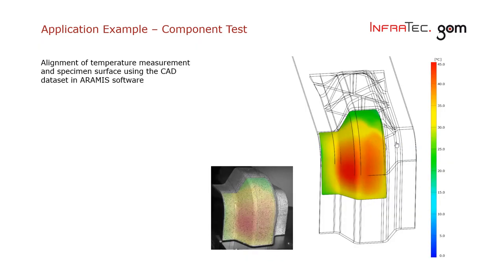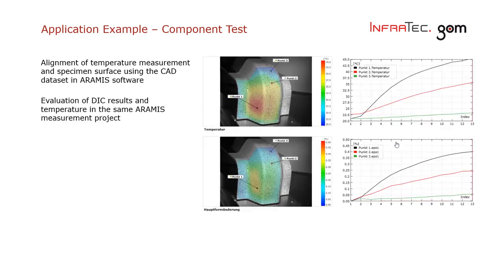Here we would do it with a CAD data set, basically to map the temperature based on the coordinates of this data set. So therefore in Aramis the CAD dataset is imported together with the temperature export from the InfraTec software. There is an alignment which is typically done based on 3D coordinates so that then the temperature data is available in the object's coordinate system and can be evaluated together in the same way as we have seen before. So the temperature data here is shown on the top image and the major strain results on the bottom image. So therefore, both datasets can be evaluated together and used for further evaluations.